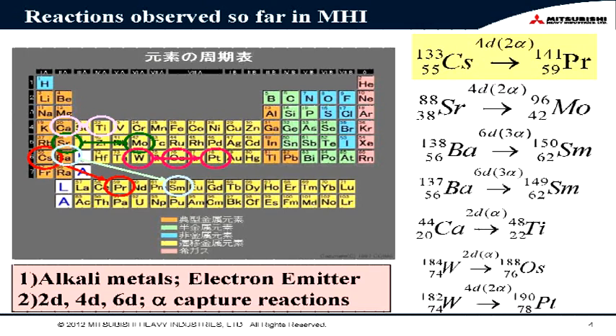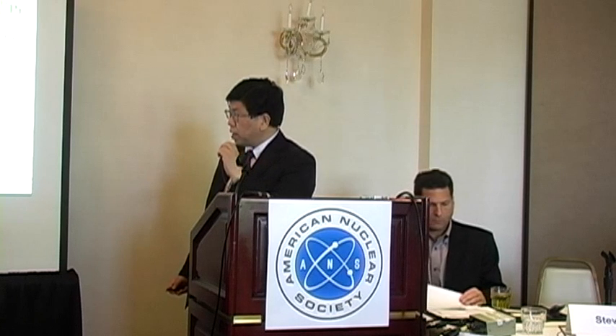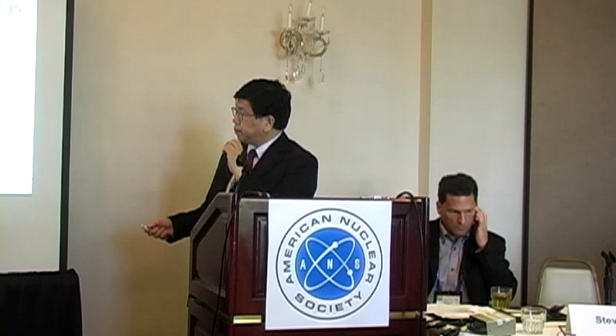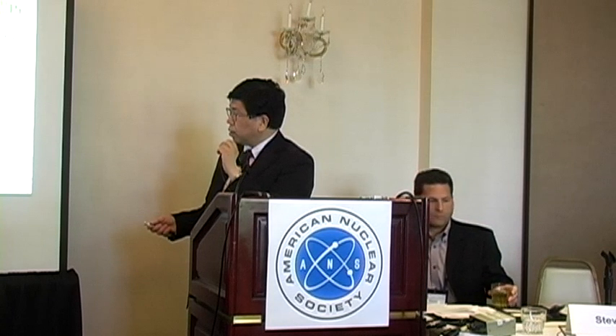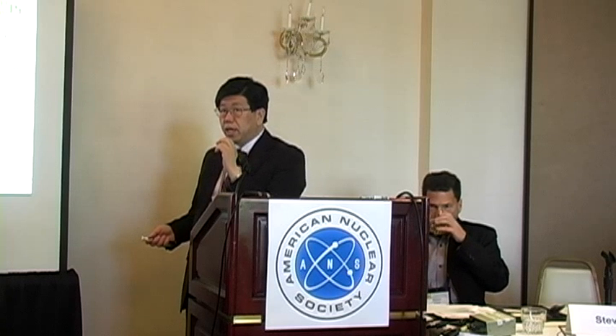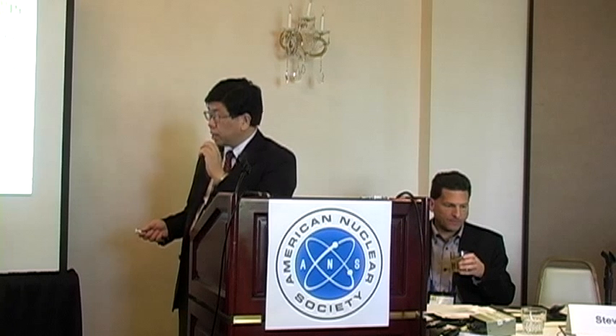This figure shows the nuclear transmutation reactions observed so far at Mitsubishi Heavy Industries, LENR. For example, cesium to praseodymium, strontium to molybdenum, barium to samarium, calcium into titanium, and recently observed tungsten into osmium or platinum. Based on these experimental observations, we can see that the alkali metals seem to be easy to transmute by our method.